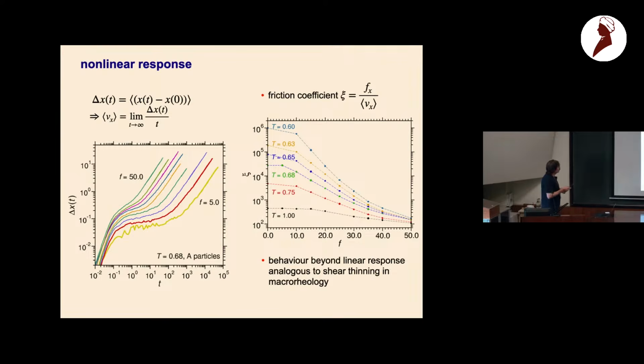Okay, now this is for different temperatures, and we see, first of all, that this linear response regime moves to smaller and smaller forces. So this regime where we see a linear response, with decreasing temperature, becomes narrower and narrower. And now it's interesting, how can we characterize these stationary states in the nonlinear response regime?